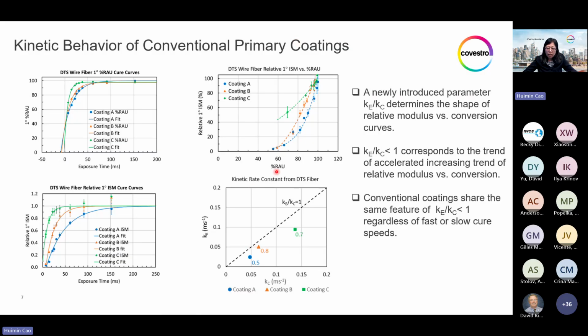For example, coating A at 80% of the conversion is only reaching 25% of the modulus, and at 90% of the conversion still only about 50% of the modulus buildup. This may lead to a wide scattering of your coated fiber primary coating modulus, even with minor cure degree variations. And this shape of the ISM versus RAU curve is solely determined by the Ke over Kc ratio. All the conventional coatings have Ke over Kc less than 1. Even if the Kc may move to the right, meaning faster conversion, and the Ke may move upwards, meaning faster modulus buildup, all conventional coatings stay in the lower half of this graph, which means Ke over Kc less than 1.